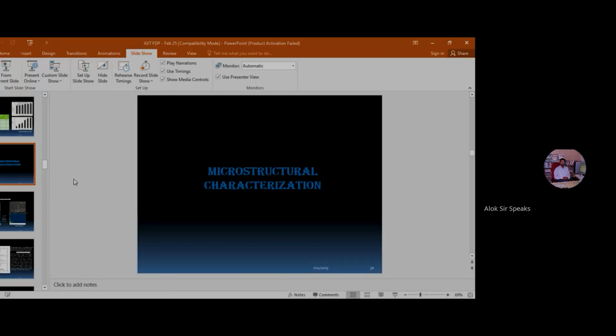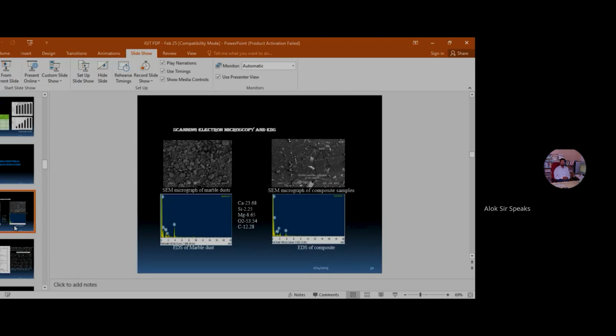Now, once the physical characterization is done, microstructural characterization is very pertinent to do, because it gives us an insight into what is happening within the composite. So we can go for scanning electron microscopy. On the left side, you can see the scanning electron micrograph of marble dust. It clearly shows the size and shape of the marble dust, which are naturally found. And on the right side, you can see the electron micrograph of the composite. You can see that the marble dust has mingled, mingled meaning not dissolved, but spread across the matrix body. And the diagram below is the EDX mapping showing the elemental features. What are the elements present in the raw material, that is the filler, and the composite. It is basically calcium, silicon, magnesium, oxygen, and carbon.